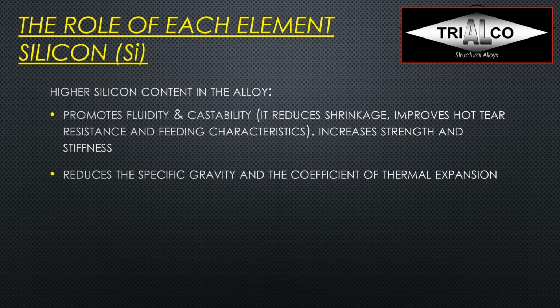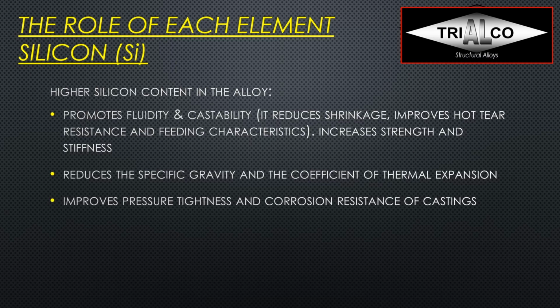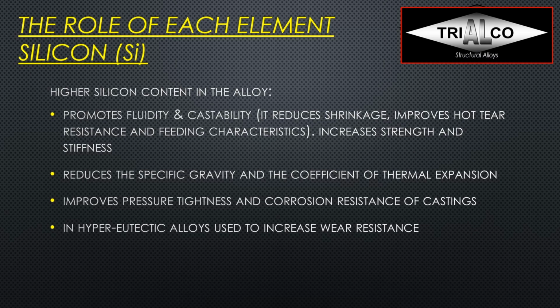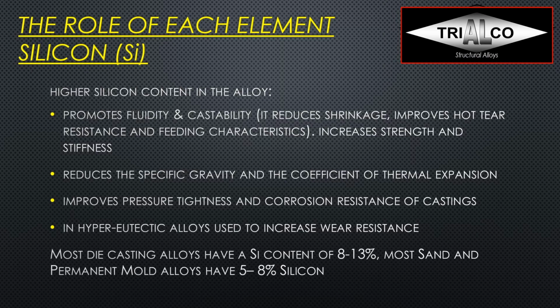It reduces the specific gravity and the coefficient of thermal expansion. It improves pressure tightness and corrosion resistance of castings, and in hyper-eutectic alloys, so above the 12.7% eutectic point, it is used to increase wear resistance. Most die casting alloys are usually in the 8 to 13% range, and most sand and permanent mold casting alloys are in the 5 to 8% silicon range.